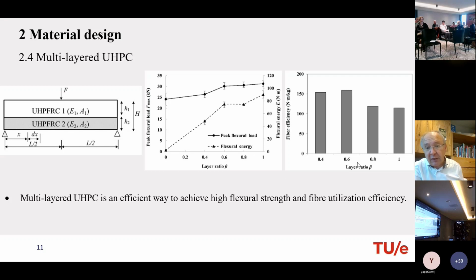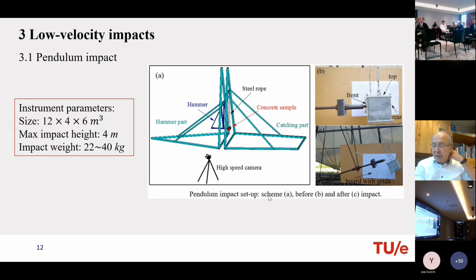We found already that when the layer ratio is around 0.6 or whatever in that range, that is optimum. That means that more or less half of the beam you don't need to reinforce with fibers, and the other half with fibers, to obtain the same properties as when you mix the fibers throughout the whole beam. So that saves already in efficiency. I will show you results later from 1 layer beams, so homogeneous beams, but also 2 and 3 layer beams.